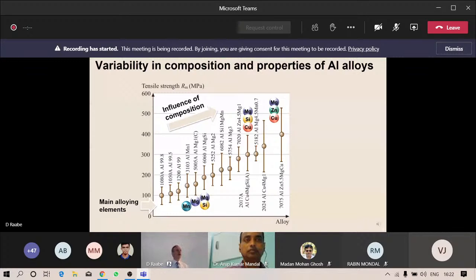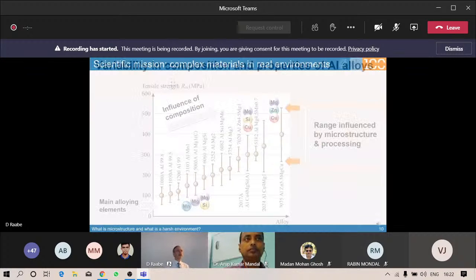And we, however, can also appreciate that when you look at the corresponding scatter bars pertaining to each individual alloy family, here shown exemplary for the 7075 alloy family, so ultra high strength 7,000 alloys, that you have a huge range of properties, here the tensile strength, that can be influenced by the microstructure and by the processing. That means that is a take-home message from any such simulation, that we have to alter and adjust and understand and simulate microstructures to serve that specific need, exploiting the variability of properties in terms of the underlying microstructure.